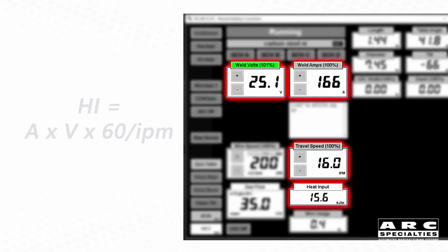Looking at the HMI operator screen, we see the average amps and volts. It's displayed the same as on the front of the power supply, average amps and volts. Using the conventional heat input method, we are sampling the amps and volts every millisecond, or 1,000 times a second. And at 16 inches a minute travel speed, we have a heat input of 15.6 kilojoules, using the amps times volts times 60 divided by inches per minute heat input formula.